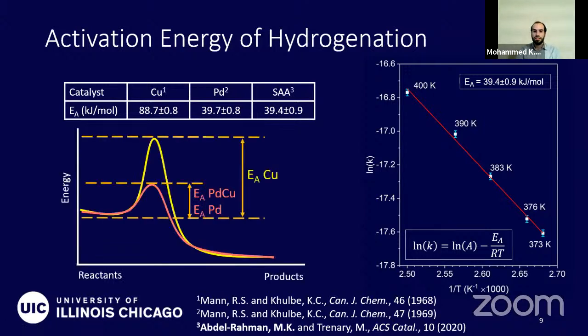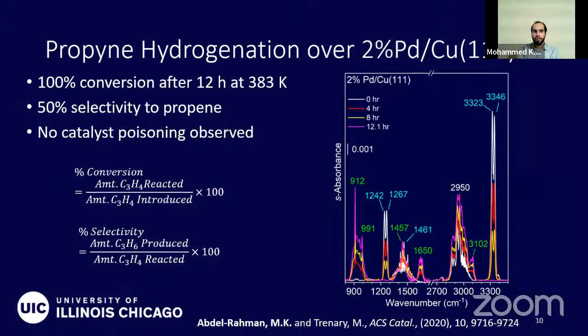And so what we've done is that by making this single atom alloy, we've effectively lowered the activation energy for the overall reaction in half. And we're showing the same kinetic dependence as pure palladium with only 2%. But we didn't account for the other 50% of the starting material.